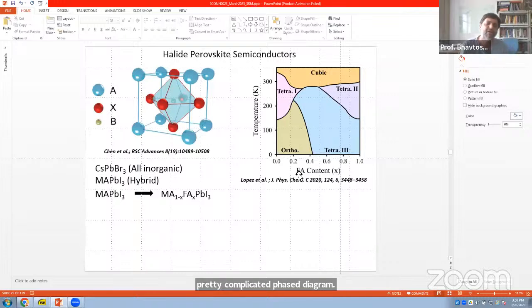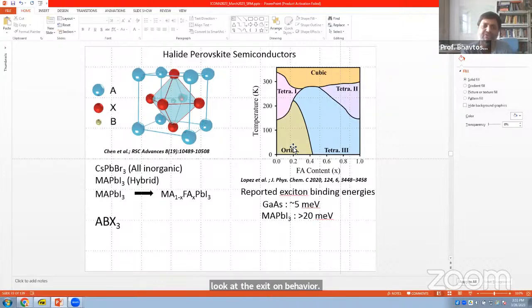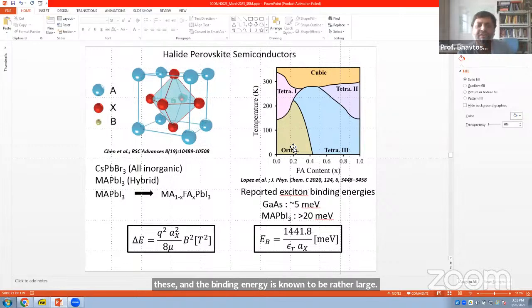This work is done in collaboration with Professor D.D. Sarma's group at IISc Bangalore. This is the phase diagram which they discovered some time ago, and others had also found this. You change the FA content in MAPbI3 from 0 to 1, and as a function of temperature you get various phases. What one would like to do is look at the exciton behavior in these phases, as I just described. The binding energy is known to be rather large, so you need large fields for this. That's what we'll try to do.